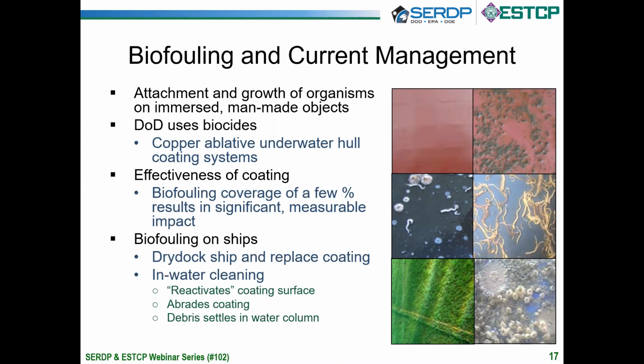The coatings are fairly effective, although they're somewhat of an older technology, but they eventually, especially on DoD vessels that don't have a very high activity profile, are overcome by biofouling and some growth will occur. It only takes a little bit of growth of biology to create a roughness that has a negative and measurable impact on ship performance, especially hydrodynamic drag, which is going to impact speed and fuel efficiency and these sorts of things. So we mitigate this fouling